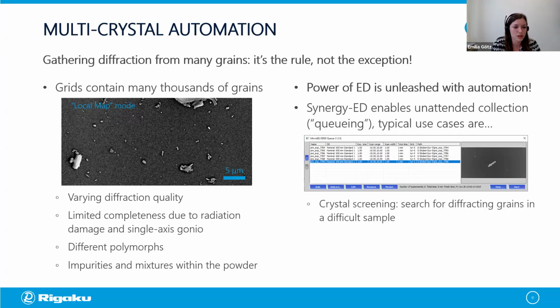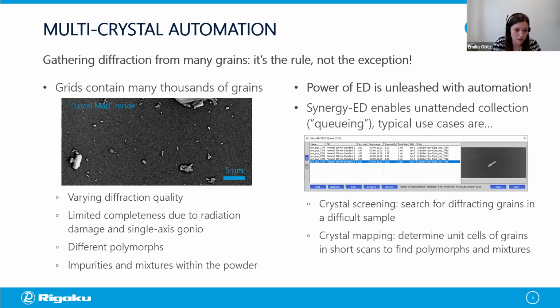And some typical use cases are just simple crystal screening, where you would go up to even hundreds of crystals and just take a single short diffraction snapshot to assess whether or not it gives a good quality diffraction pattern. And then after it has gone through the queue, maybe spending an hour on it, you can revisit the crystals that have a good diffraction data for full data collection. Another very important case is crystal mapping.